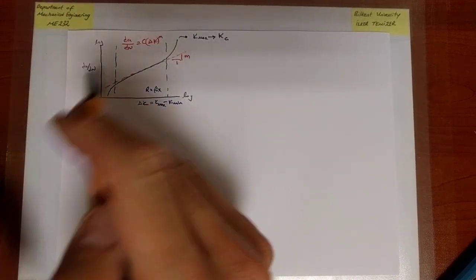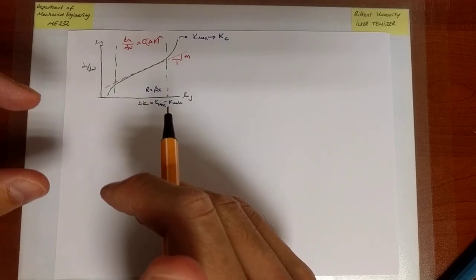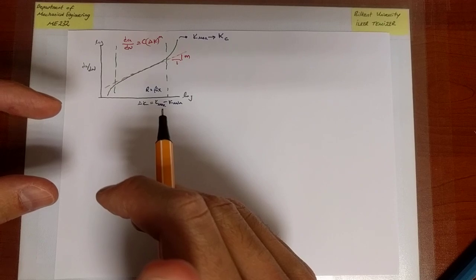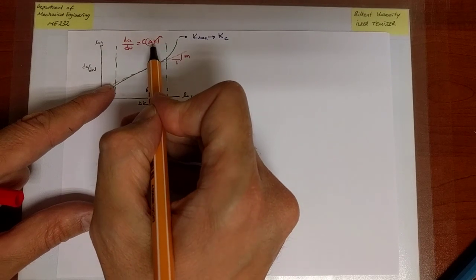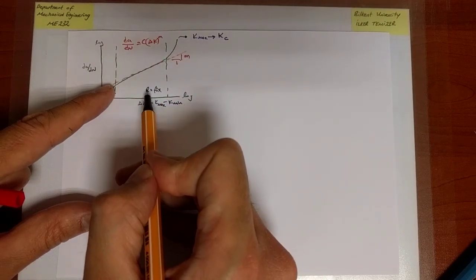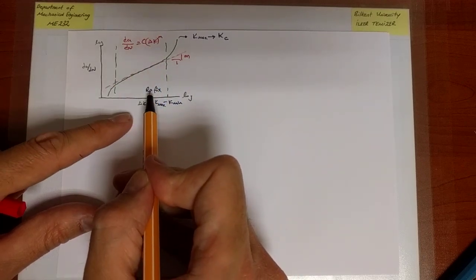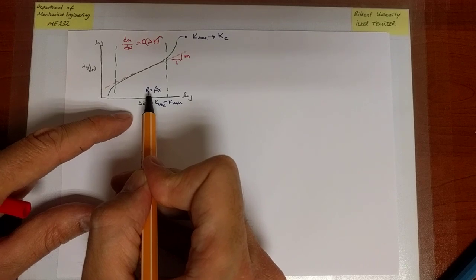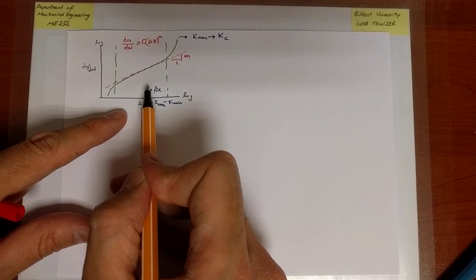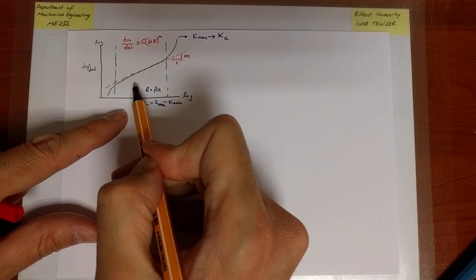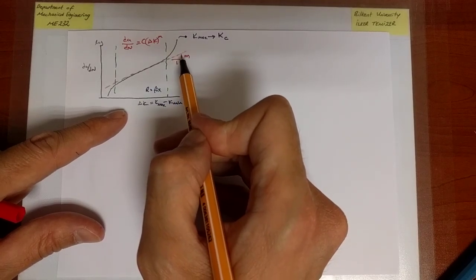And the crack is growing because the load changes between S min and S max. So I have two parameters that control the nature of the load profile, and we have replaced those two parameters by the stress range, delta S, which goes into delta K, and R, the stress ratio. Now, the stress range is already within delta K, and therefore I am trying to now additionally incorporate the influence of R. And moreover, I'm going to try to do that within the intermediate range. It's also certainly a concern in the high range, but in the high range, I have a more important concern.